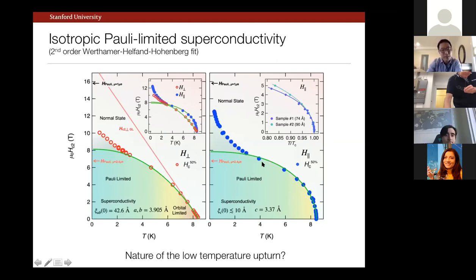So let me tell you what we think we can say confidently and then end with some open questions. The first thing that's rather remarkable about this layered superconductor is that this is now just overlaying the two directions side by side. It's remarkably isotropic. Right? So think about what you know from the cuprates, or if you're less familiar, also strontium ruthenate, or cobalt oxide, the sodium water-intercalated cobalt oxide. These are all very strongly anisotropic. Okay? In this case, at least experimentally, we certainly see that it's quite isotropic. And I think the simple understanding that immediately pops out of our analysis is that we're dominated by the Pauli limit. So it's the spin response of the system that is largely isotropic that sets the scale for the upper critical field.